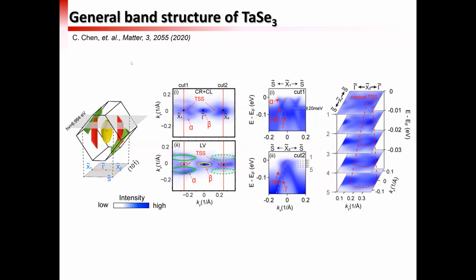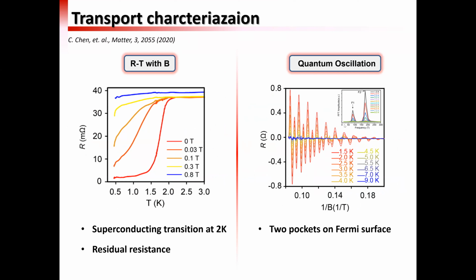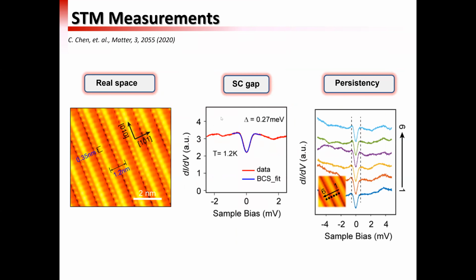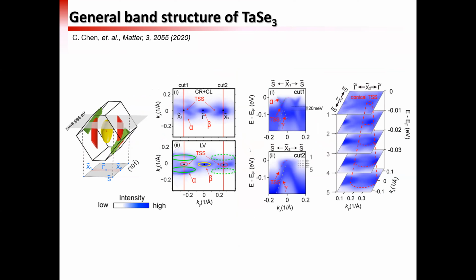So then we just take an ARPES measurement on this sample. We first did this DFT calculation, which shows there are 3 Fermi surface pockets in the bulk Brillouin zone, and if we cut through here, we can see this quasi-1D behavior is pretty clear, and you can see the horizontal line. Of course, it's quasi-1D, it's not exact 1D. So we can see there's one pocket at alpha, which is the X point, and one pocket at the gamma point. This is consistent with the quantum oscillation result that shows the 2 periodicities that correspond to the 2 bulk pockets.